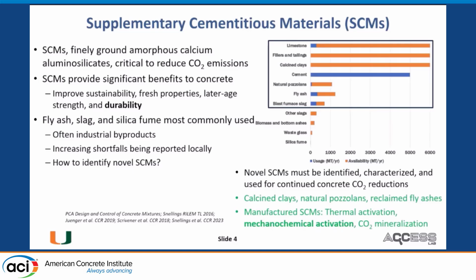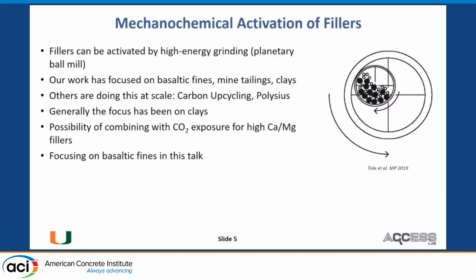But at the same time, a lot of people are looking into manufactured SCMs, Terra CO2 as an example, where thermal activation, mechanochemical activation, or CO2 mineralization can be used to potentially transform or improve inert feedstock into reactive materials. So my focus is going to be on mechanochemical activation, and largely I'll talk about basaltic fines and their mechanochemical activation. Essentially, mechanochemical activation is high energy grinding. We do it in a planetary ball mill.